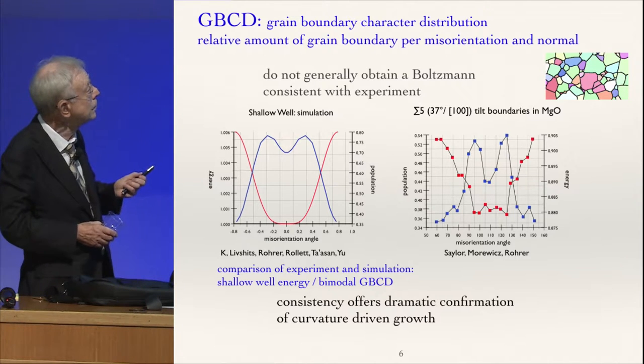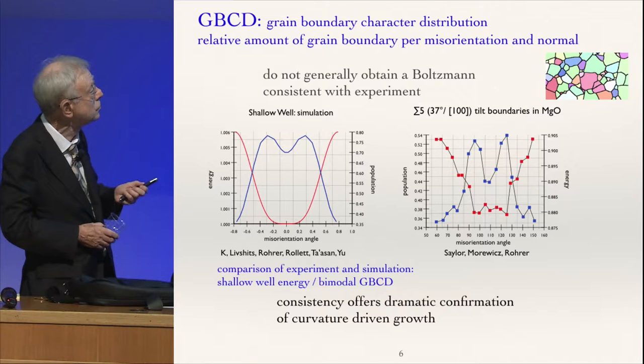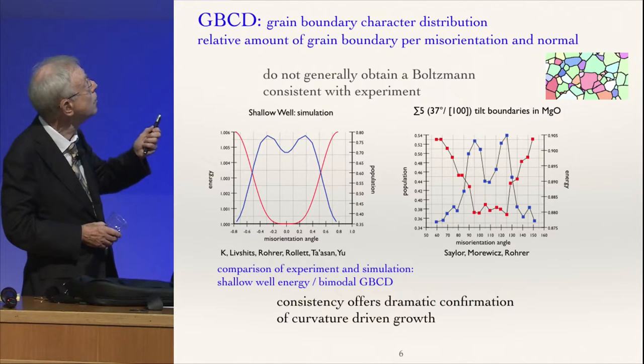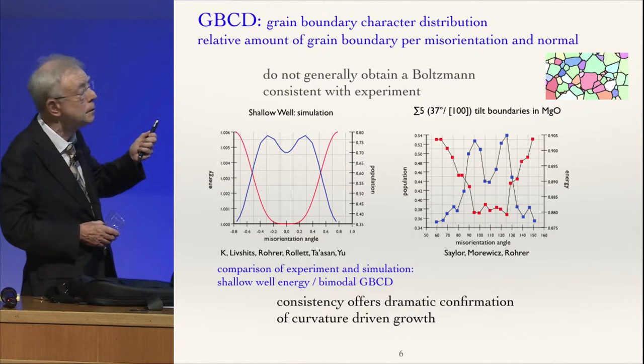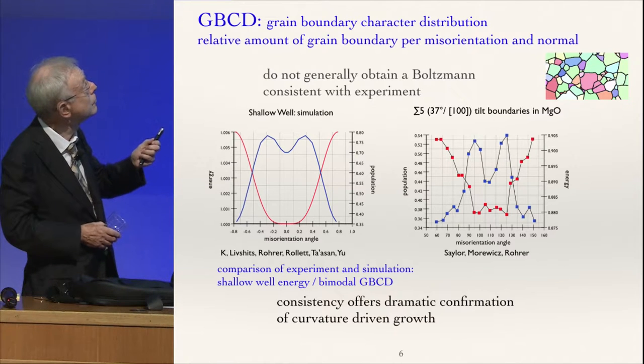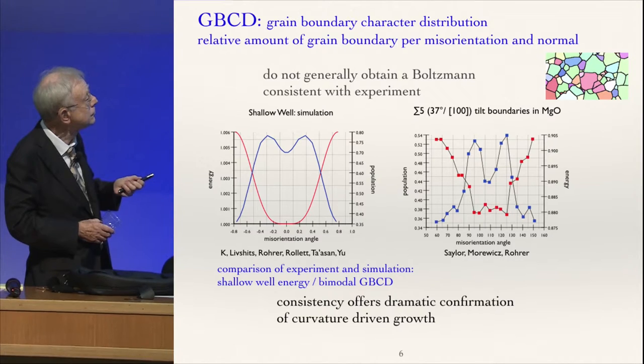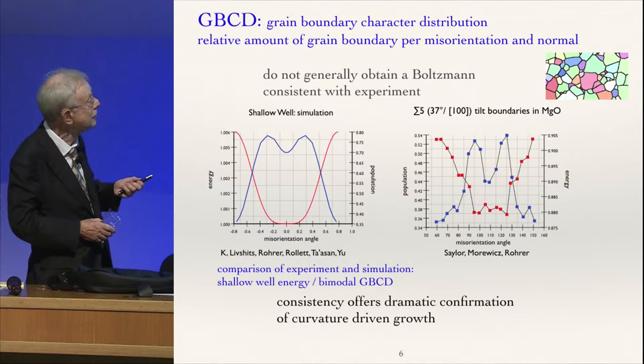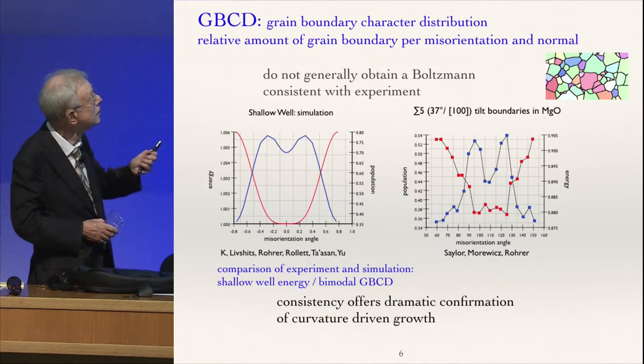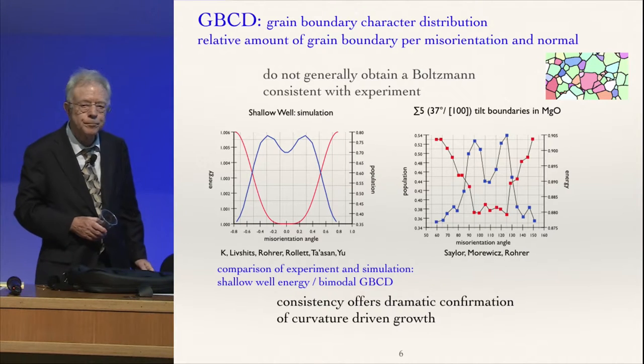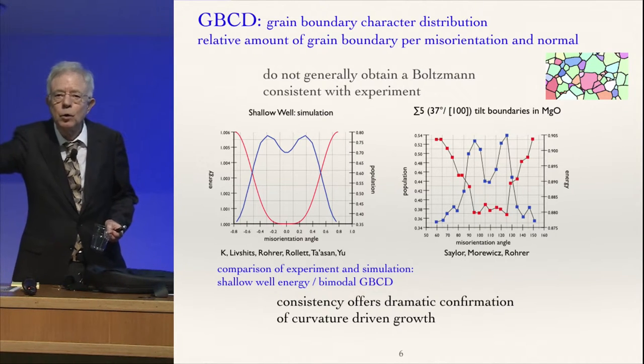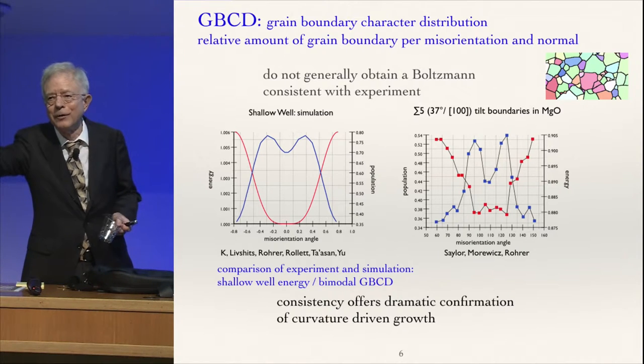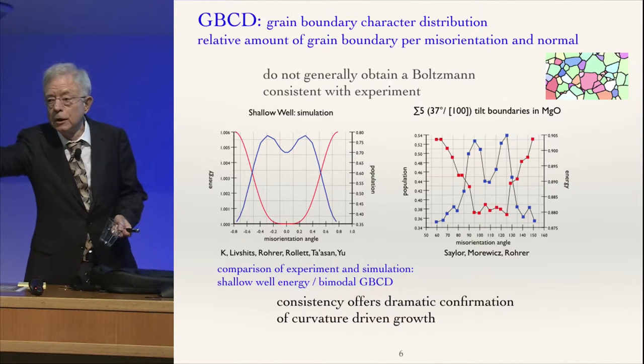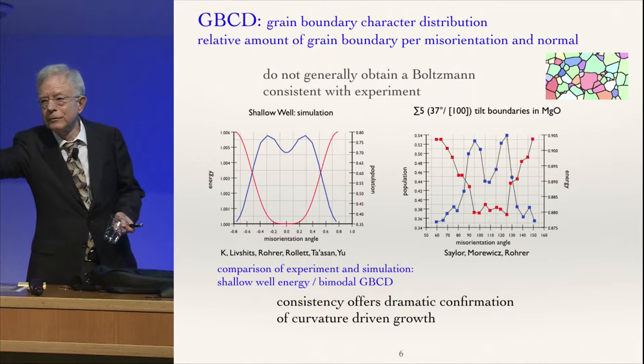So in comparison of experiment and simulation, shallow well energy, bimodal GBCD, and we call this the grain boundary character distribution. We didn't make up the name. It's the relative amount of grain boundary per misorientation and normal. And so here you see consistency that offers dramatic confirmation of several things. Among others is that this curve on the left, the ones we produced, were executed with a reasonably large scale, well, not very large scale simulation of a curvature-driven growth. And so here is a statistic derived from a theory, and this is just a statistic.